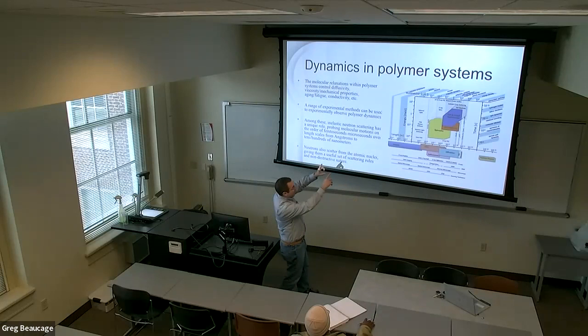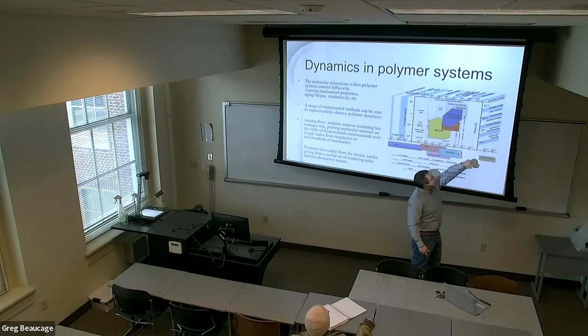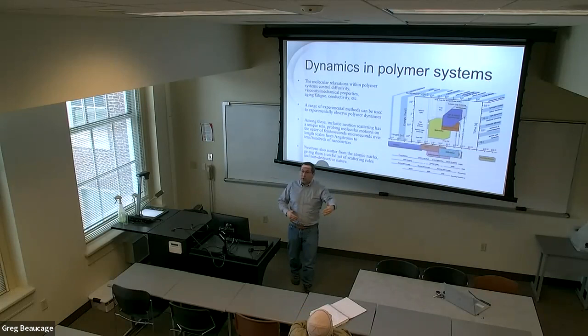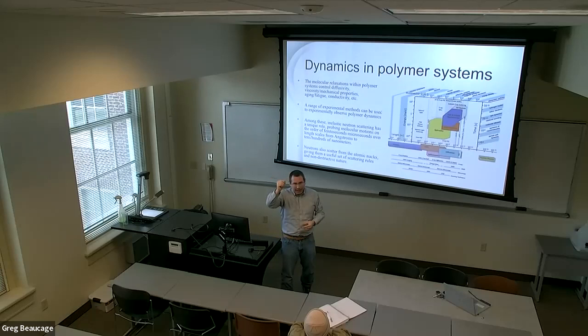But if you're looking at, say, chain dynamics, then you need to go to spin echo. Or if you're looking at molecular vibrations, then you need to be in time of flight. Molecular vibrations are fractions of a picosecond, with displacements on the order of an angstrom or less. You simply need to make sure that what your experiment is telling you matches up to the time and length scale of the physical process that you care about. That's the trick here.